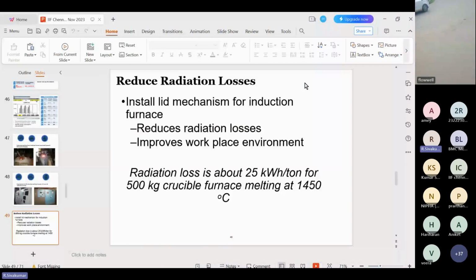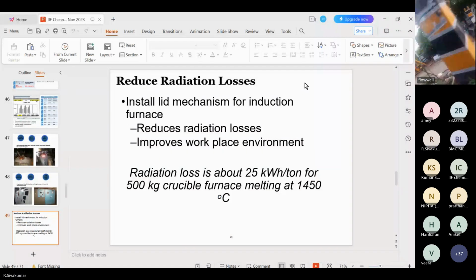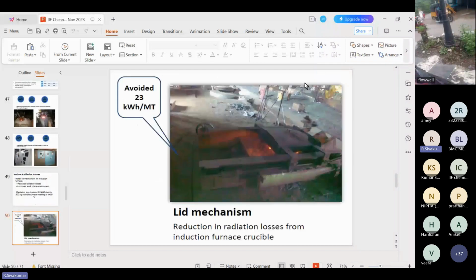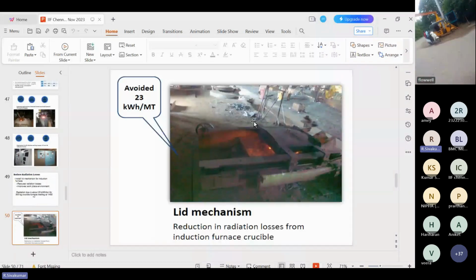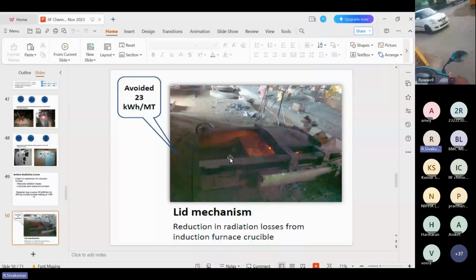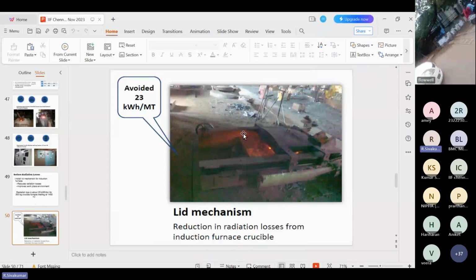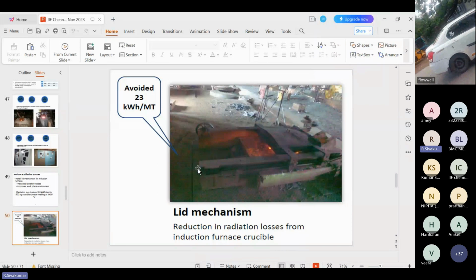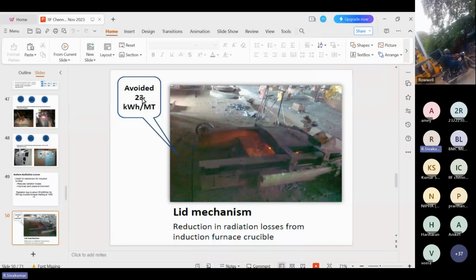So the radiation loss is 25 kilowatt per ton for a 500 kg crucible furnace melting at 1450 degrees. So a lid mechanism can be used, a lid cover placed on the furnace, so that 25 units can be saved in a ton. These are the lid mechanisms adapted in various industries in the northern cluster. It was prepared by the foundryman himself based on operator flexibility. So it avoided 23 units per ton.